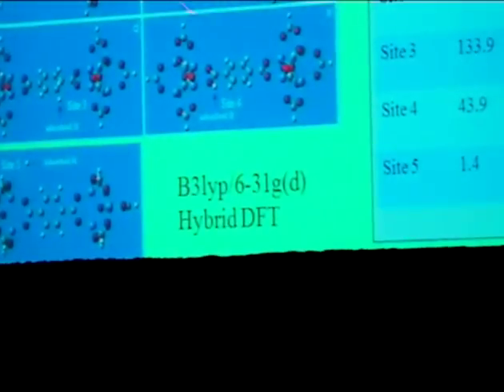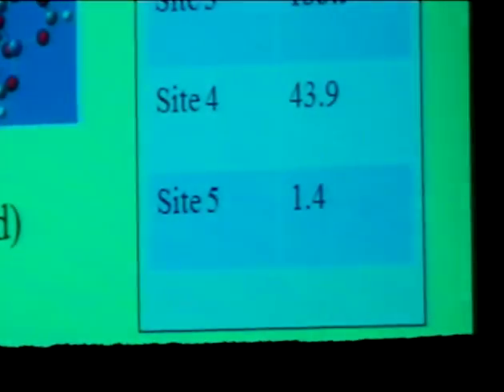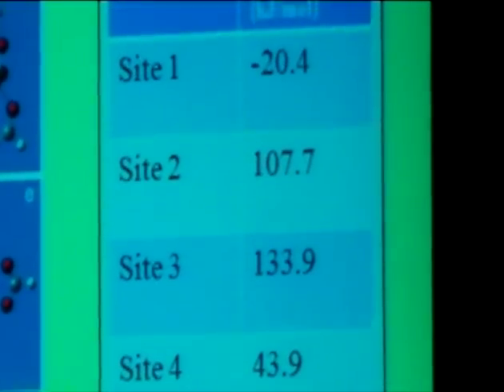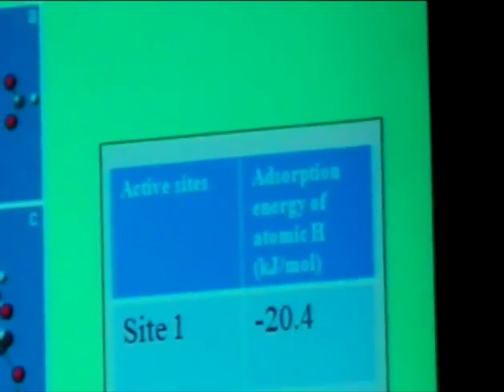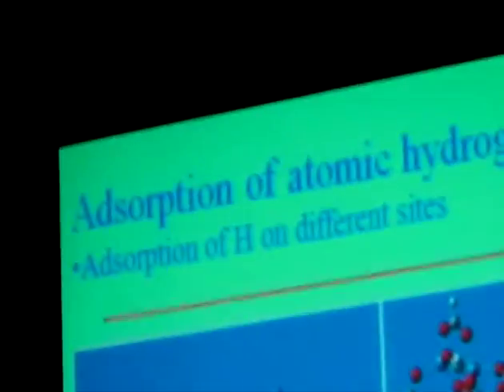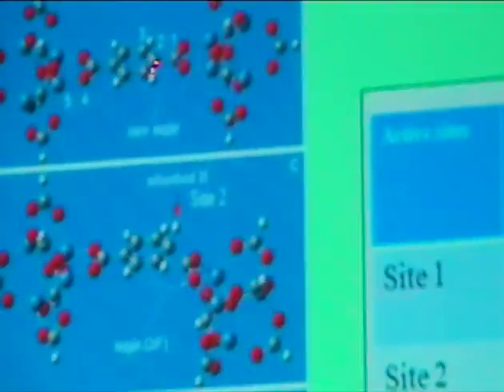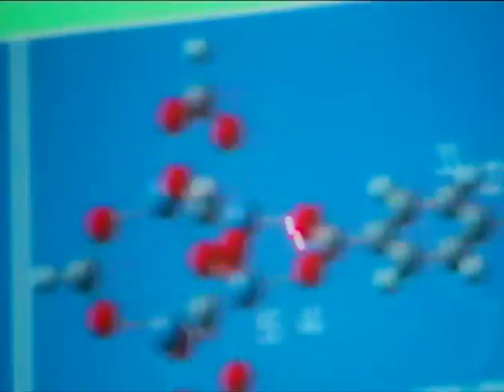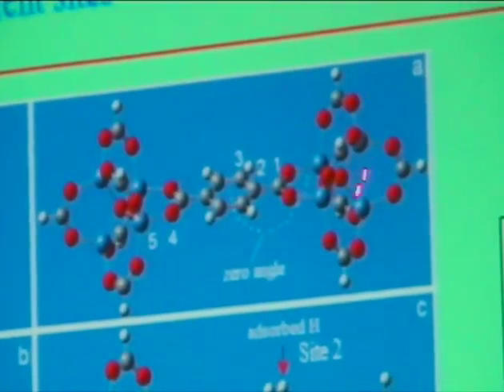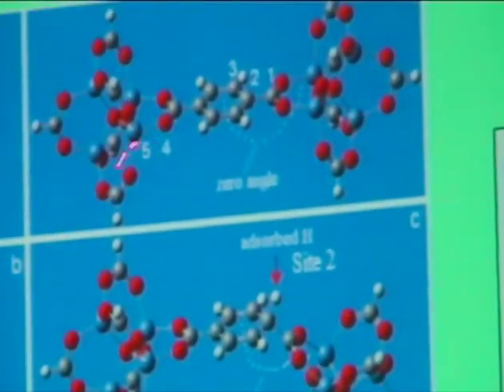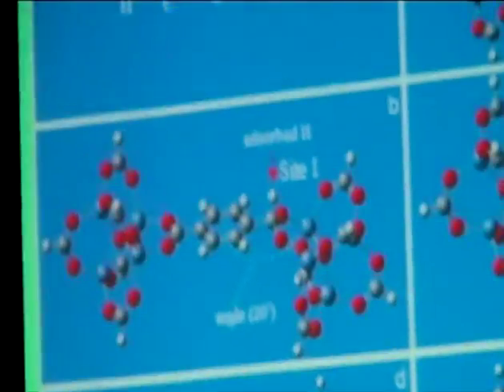So that's the question. Firstly, we use the DFT calculation to show how strong the interaction is between the atomic hydrogen and the MOF. If you see this, we pay attention to the active sites of the MOF-5. You can see there are 6 carbon atoms, and each one can get 1 hydrogen atom. And the oxygen can also get hydrogen adsorption. So in total we have 5 types of hydrogen sites: this is 1 here, 2 here, 3 here, 4 here, and 5 here.